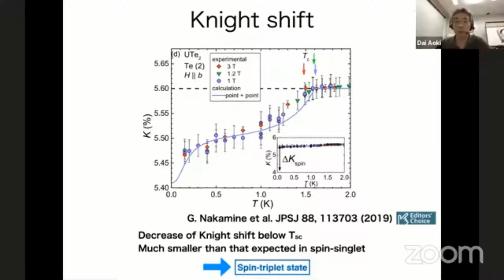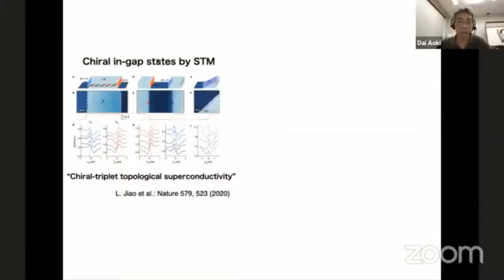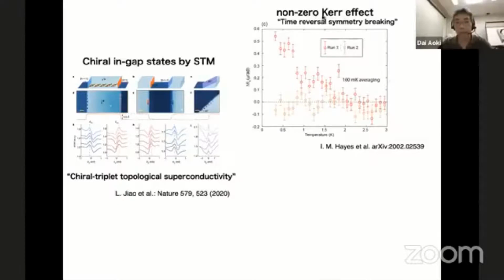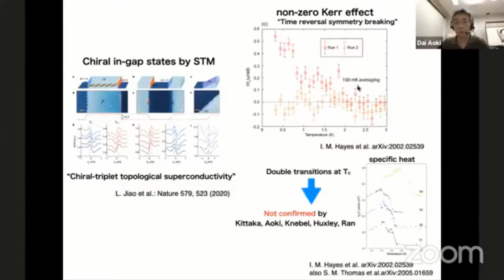Another interesting point, not from our data, is that STM data shows a chiral in-gap state detected by a group in America. Also a non-zero Kerr effect is detected, and from this they conclude that the time reversal symmetry is broken. They also show the specific heat curve, which shows the double transition. This double transition is also reported by the Los Alamos group. I think in the previous webinar at SCES, she showed the double transition, I guess. But this double transition is not confirmed by our group or Andrew Huxley's group or others. So this is still an open question.